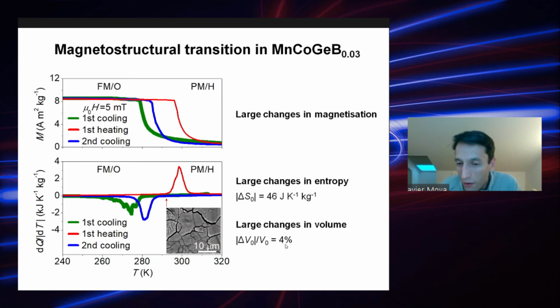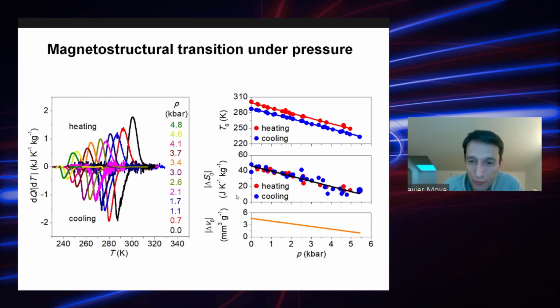What we wanted to do is to investigate what happens when you apply pressure instead of heat. Because as I said, the volume changes in these materials are 4%, so these are very large in a solid material. And this is detrimental for magnetocalorics because the sample will crumble, but it's actually beneficial for barocalorics because the heat exchange will be better. So what we did is we synthesized these samples. We did calorimetry as a function of pressure, which is shown here. So you can see that the transition is shifting down. So this is an inverse barocaloric material.